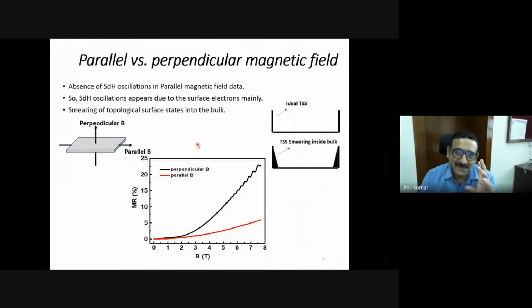So let me just show some more interesting results here. You can measure the magnetoresistance of this sample as a function of applied magnetic field. And you see that in this crystal, as the magnetic field is increased, the magnetoresistance increases, then it starts showing some kind of an oscillation. Sometimes we can think, oh, it's some oscillation, some noise, something like that, we can discard. Or we can extract physics out of it.